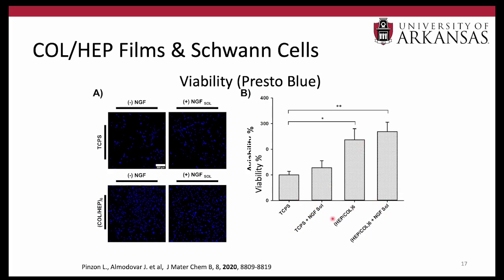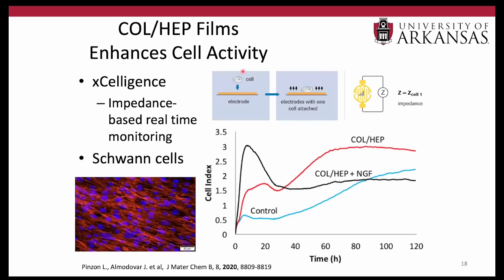And that was really intriguing to us, and so we decided to investigate further. We did some proliferation assays and saw that it wasn't necessarily due to cell proliferation. So we decided to do this study using an apparatus that is an impedance-based system where the cells are cultured on an electrode, and the impedance is recorded as a parameter known as the cell index. As the impedance or the cell index increases, that means there are more cells in contact with the electrode. The powerful thing about this apparatus is that we can monitor the behavior of the cells in real time. And what we saw was quite interesting.